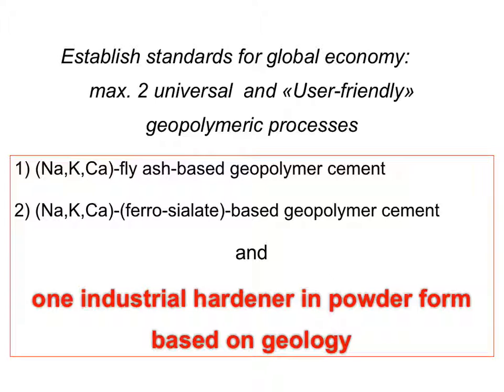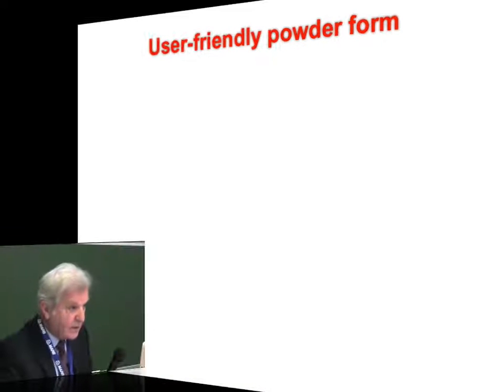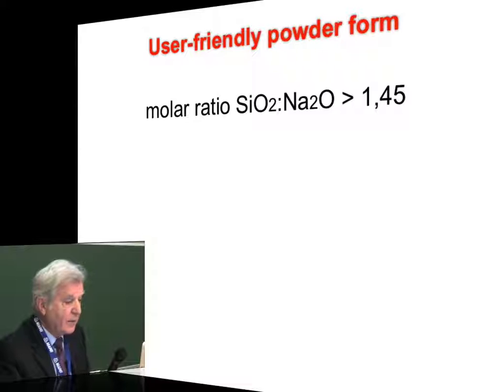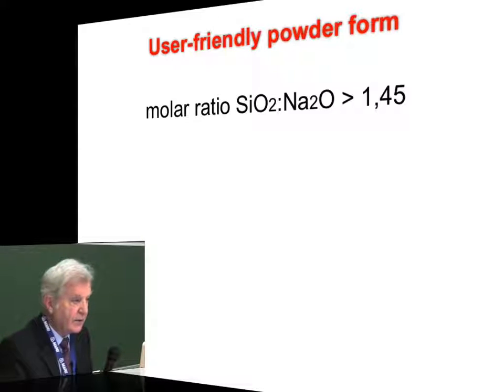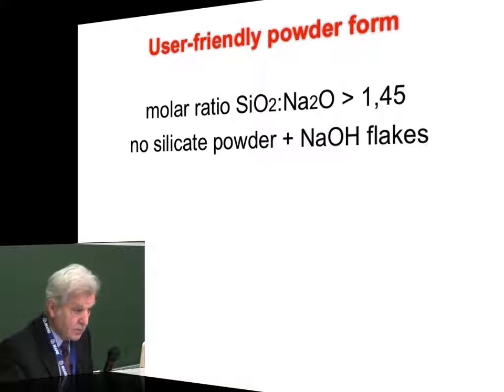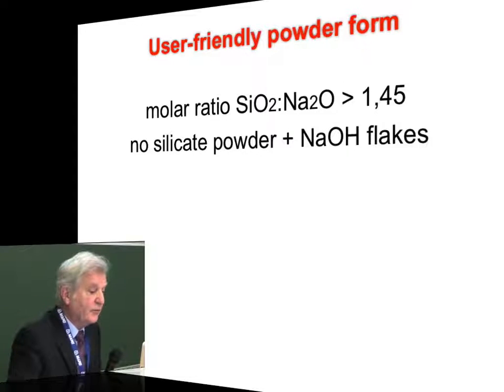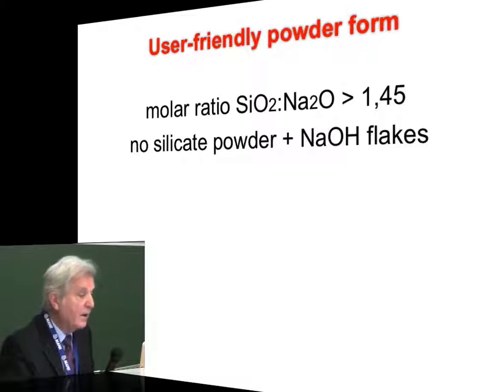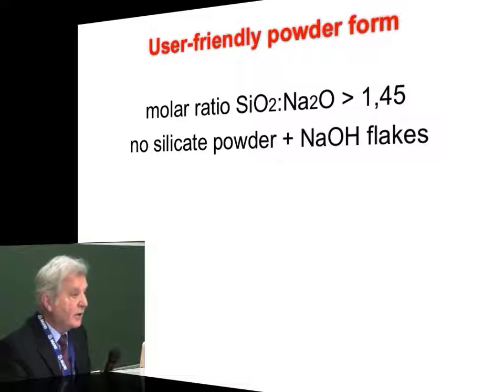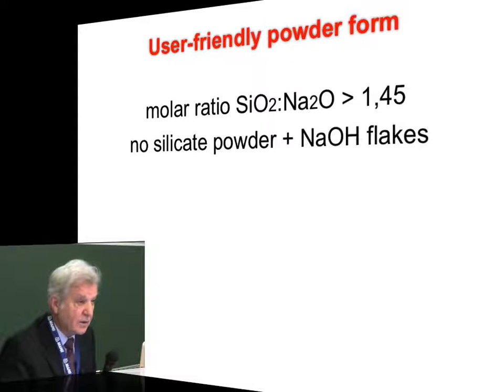The third element is the industrial hardener, in powder form, based on geology. It must be a user-friendly powder form with a molar ratio of at least 1.45. It must be higher. I don't want a mix made of powdered silicate that has a very low ratio and NaOH flakes. You'll find in the literature a lot of papers describing, I have invented a dry mix for geopolymer cement. And when you look at it, it is potassium or sodium hydroxide flakes ground with metasilicate and so forth. And this is user hostile. I want innovation. Yes.